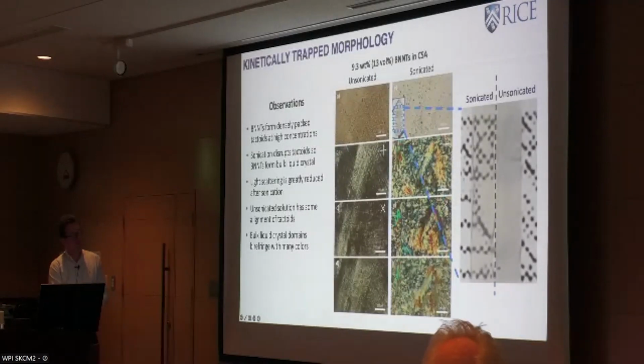We do think that there is something that we've never seen in carbon nanotubes, this kinetically trapped morphology. So this is a high concentration of boron nitride nanotubes in chlorosulfonic acid. It's about 13% by volume. This is before sonication, and this is after a little bit of sonication when the material is already in the capillary. So you see much larger structure. You start seeing color, which you don't really see before sonication. And if you put it in front of an image, you see how the unsonicated solution has a lot of scattering, whereas the sonicated solution loses the scattering.